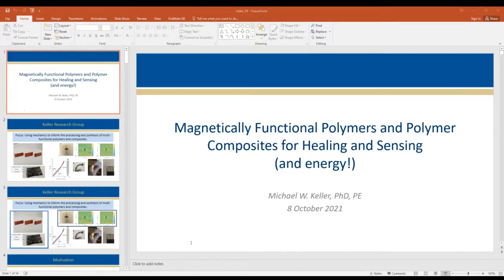So we picked up an induction heating board off of Amazon. We hot rodded it with capacitors designed for welding units. We immersed it in a mineral oil cooling bath and ran it that way. So it was kind of an aggressive process. It took my poor grad student a better part of 3 months to build this thing. We kept blowing up capacitors because of heat, but eventually he got it done, and we built this little pancake coil, and we're able to get these detection results.